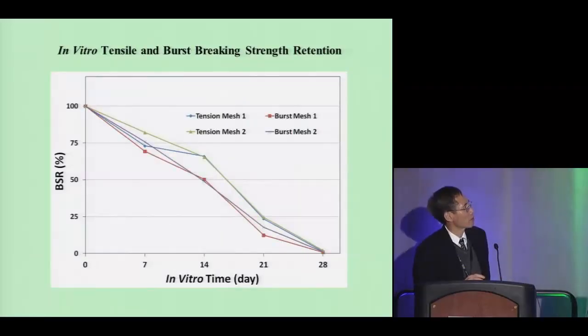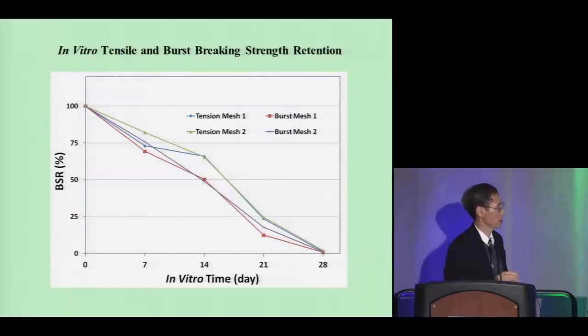Yeah, we presented strength decrease as breaking strength retention versus in vitro time. And there are two tests, as you can see here, burst and tensile. Basically, if you normalize your tensile strength by your initial strength, the percentage of strength retention follows the same kind of trend. Essentially, they are the same in this case.